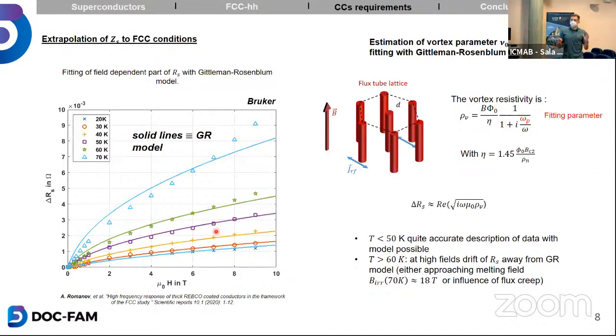I think this can come from 2 different things. First, our model doesn't include flux creep, so no thermal effects are included. That's why it's kind of natural that we deviate slightly from the model at higher temperatures. And second, we might also approach the upper critical field for some superconductors at higher temperatures at 9 Tesla. And this is also not considered in the model, and that's why we see a deviation from the model.